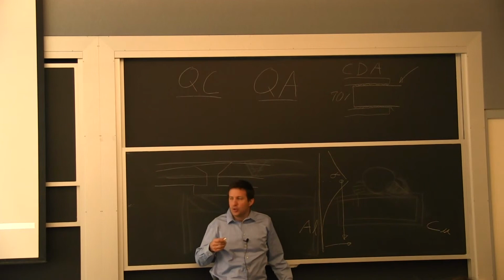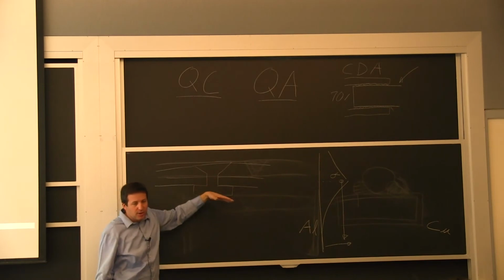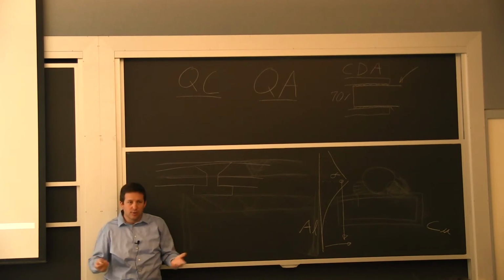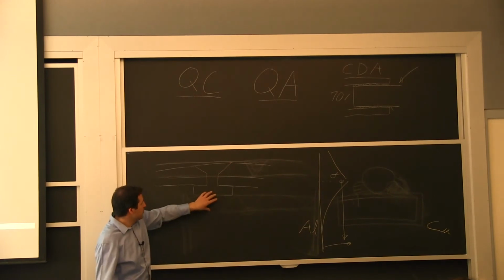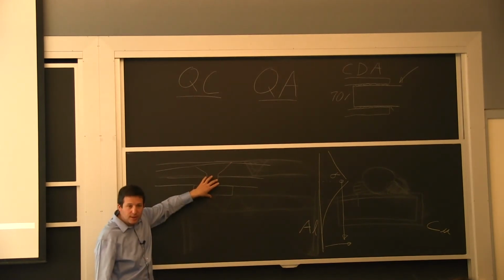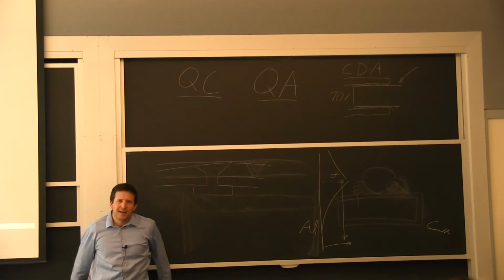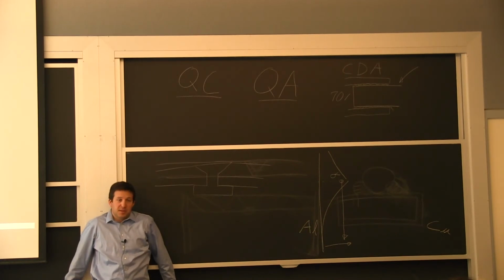And what happens when you install, when you go through the process of making that deformation, you actually activate the aging process because you've got all these dislocations, all the internal material components moving and helping form these little precipitates that harden your material. So it was kind of a win-win. You wait until you're ready to complete your joint, and as you complete the joint, you start forming the precipitate. Then just at ambient temperature, it will age to at least 50% higher yield strength than what you started with. To me, it was impressive.